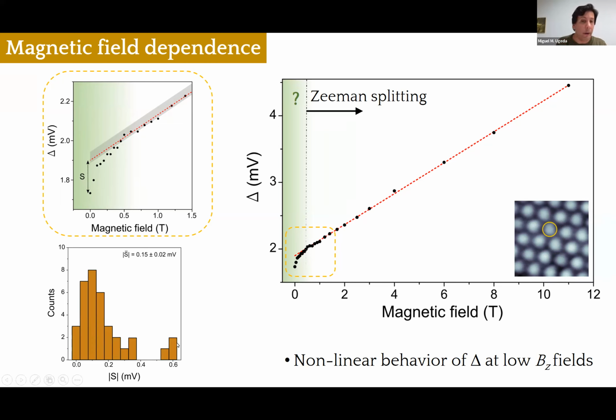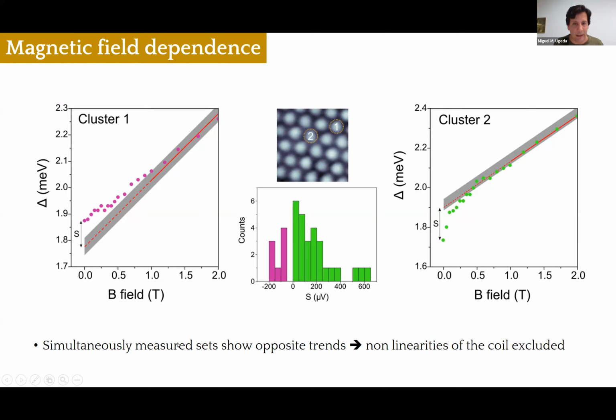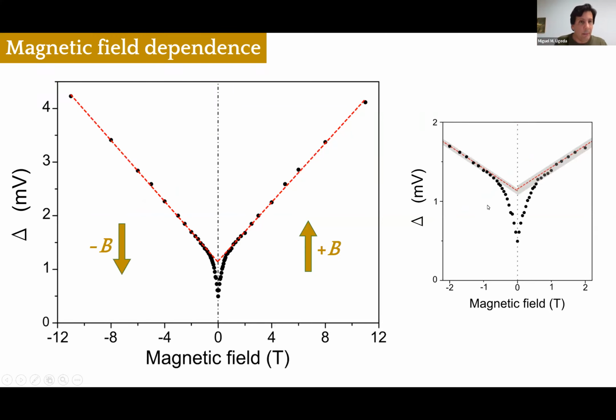Another possibility could be that the coil that we have in the STM should give not a linear response, but we are sure that this is not the case, and these non-linearities of the coil can be excluded. And the reason is because we have measured a totally different behavior, an opposite behavior in clusters using the same tip. So here I show you an example. You have two clusters in which we have repeated the experiment. In cluster one, the trend is going upwards with this slope, whereas in the cluster next to it, the tendency is going upwards, but the slope is different. So we can exclude any instrumental artifact.